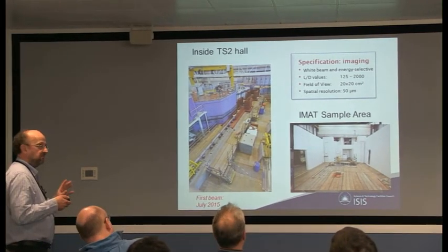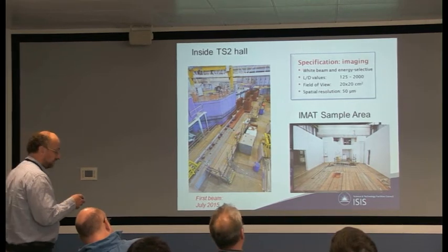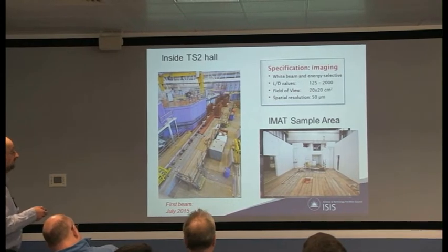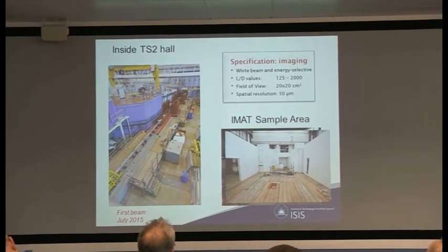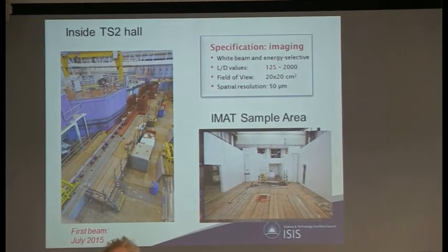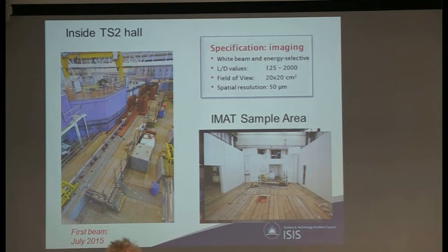Assuming that you will potentially be mostly interested in the imaging part of IMAT, here are the main parameters. We will work with a white beam, but we will have the option to do very good or good energy discrimination. The beam size is 20 by 20 centimeters maximum. If samples are bigger, we will need to scan. And the spatial resolution that we aim for is 50 micron. That is not as much as you will get with X-rays, of course, but the reason for this resolution limit is what Steve said. It is the intensity that we have available.